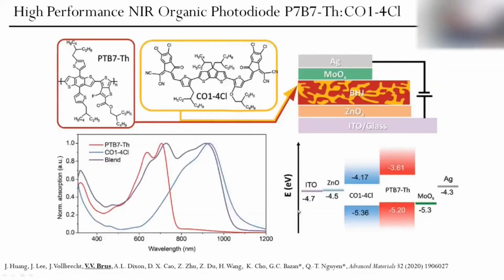So one of the examples of these organic photodiodes I was working on is also a mixture of some donor and a non-Fullerene acceptor material with a very narrow band gap. That's why we can absorb at long wavelengths up to 1100 nanometers. So this is the so-called near infrared region.